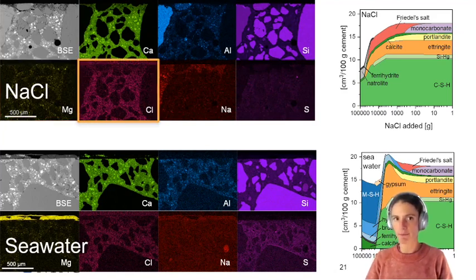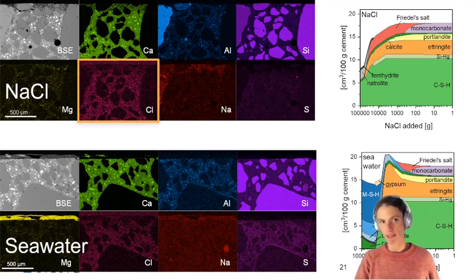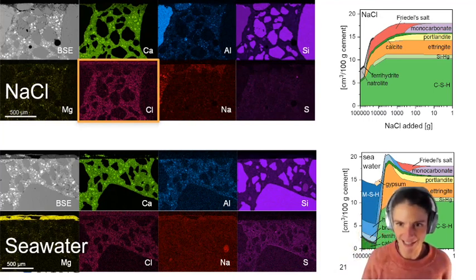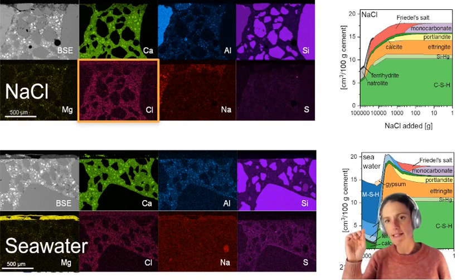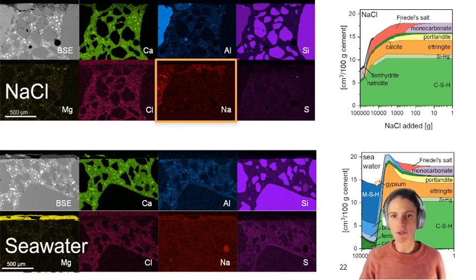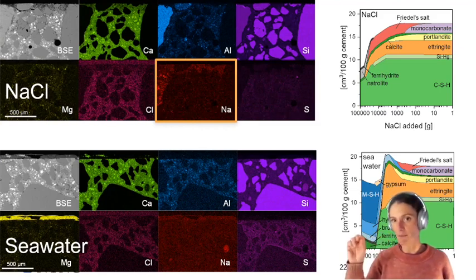For chloride, the chloride map shows that we have chloride enrichment in the cement paste, so it's the negative of the silicon map, though there's less chloride in the top, so we have lower chloride levels at the surface. For the sodium, you can see that there's a sodium enrichment in the top of the cement paste. So at the surface, we have a slight sodium enrichment.